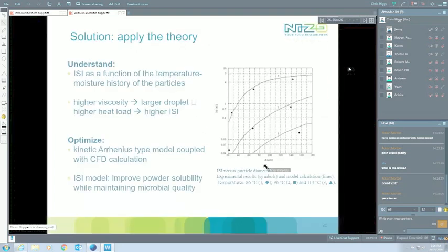And how can I basically select optimal conditions? You can start looking at what we saw earlier. What droplet sizes will I get? What risk if I increase my viscosity because of heating, for instance? How will that relate to insolubility development, and how should I adjust drying conditions? If I know that with a heat treatment my droplet size is going to increase maybe from 60 up to 120 micrometers, I know that's going to give a massive increase in my insolubility development, so maybe I should drop my temperature a bit to compensate for that and make sure that I stay in the safe zone. So by using models like that, we can actually play around with it a lot, get the right insights, and be able to choose the right conditions.